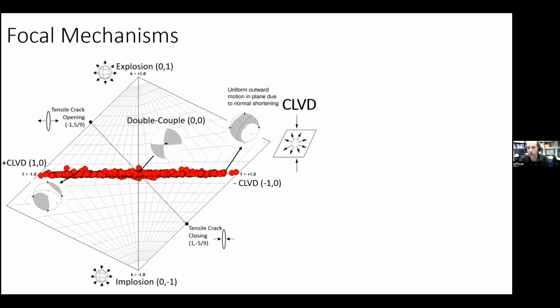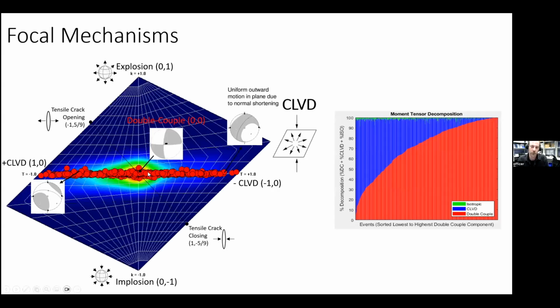So now if we look at our data, basically it falls right along this line. We have a bunch of double couples at the center, which are piled up on top of one another, but we also see a significant amount of CLVD components, and I'll explain why that's the case in a moment. So here's just the density plot. There are so many piling up in here that you can't even see through the dots to see the red part of the heat map. So we have mostly double couples, or shear fractures, but we also have a significant part of these CLVD components along the sides here. And if you look at this here, each one of these is just a bar graph. The important part is we don't have any isotropic components, any explosions or implosions.